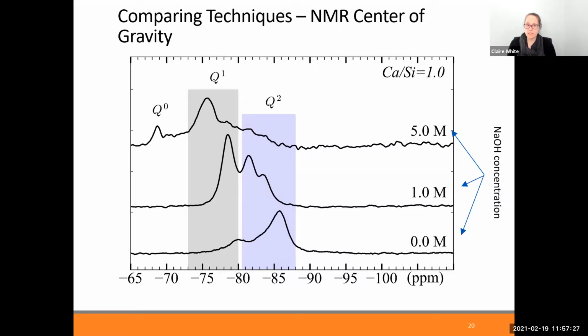the assignment of these peaks came from looking in the literature at existing analysis of similar synthetic gels that people have done in the past. We were doing this in collaboration with Jorgen Skibsted, who does a lot of cement NMR analysis out of Denmark. Beyond that, I can't provide exact information right now, but I'm fully aware that it's the local bonding environment around the silicon centers that can change the chemical shift. The way this was assigned with my postdoc was based on his existing knowledge of NMR, working with Jorgen Skibsted, and also literature data.